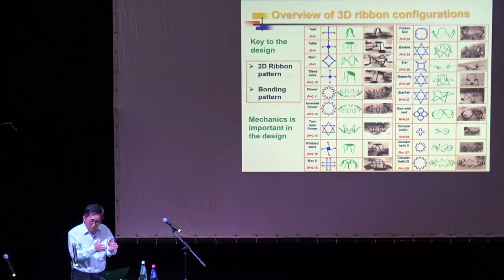In the mechanics model, there's no parameter we can fit to the experiments. So why does the theory agree so well with experiment? Two reasons. Number one, the material model is simple. This is silicon, it's purely linear elastic. There's no plasticity, no other behavior, just a straight-line, linear elastic model.